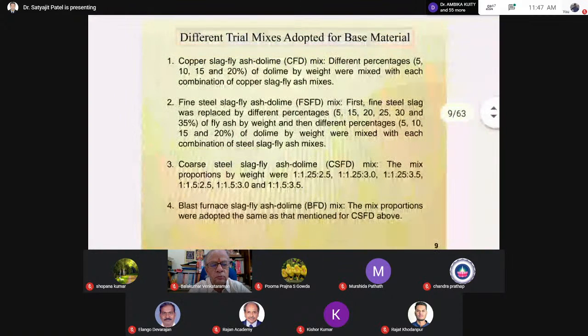Then the different trial mixes adopted for base material: the copper slag fly ash mix, with different percentages like 5, 10, 15, 20% dolime added to each combination of copper slag fly ash mixes shown earlier in the sub-base material. So for each combination of copper slag fly ash mix, different dolime has been added. Similarly, for steel slag, fly ash has been added at 5, 15, 20, 25, 30 and 35% to fine steel slag. And then different percentages of dolime, 5, 10, 15, 20%, have been added.